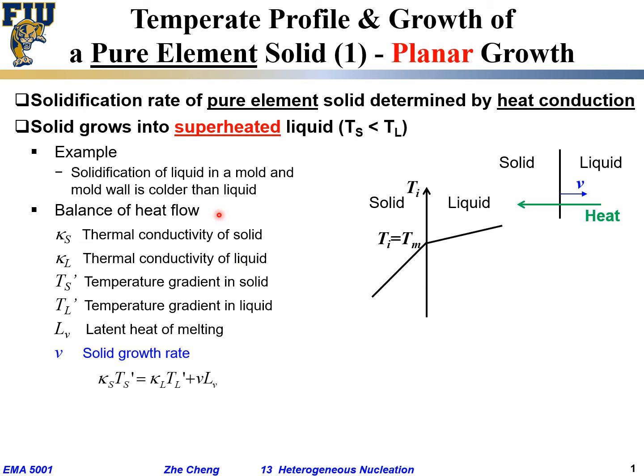So when you consider the balance of heat flow, we would get an equation something like this. On the left side would be the heat that is conducted away from the solid, which is thermal conductivity of the solid phase times the temperature gradient on the solid phase, which is the slope for this line on the left side. This is how fast the heat flows away from the solid, which would be equal to the heat flow from the liquid side, which we have two terms. One term, kappa L times T prime L. Kappa L is the thermal conductivity within the liquid. Thermal conductivity times temperature gradient within the liquid, which is the slope for this line. But that's not enough, because when liquid converts into the solid, it has to release heat.